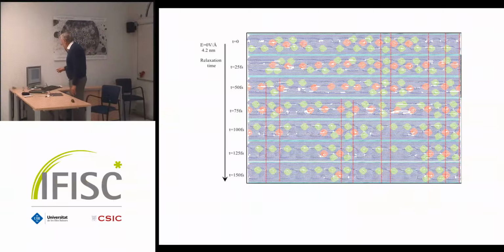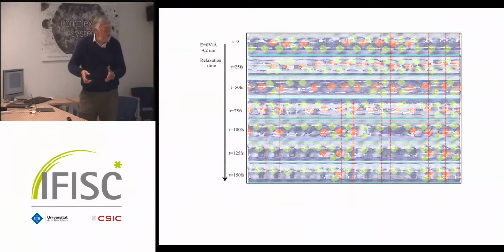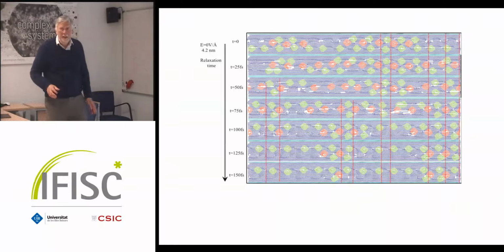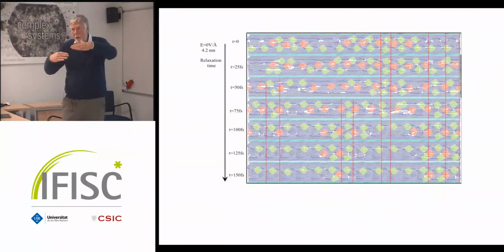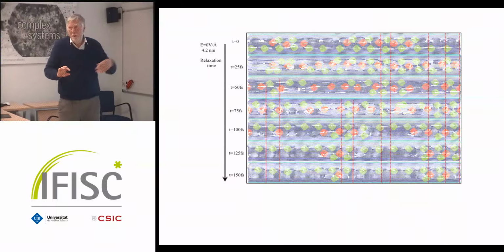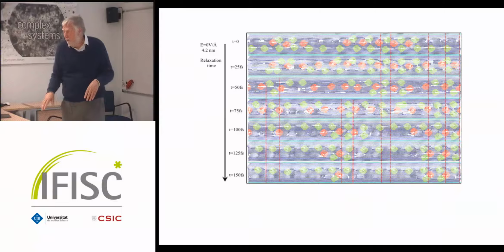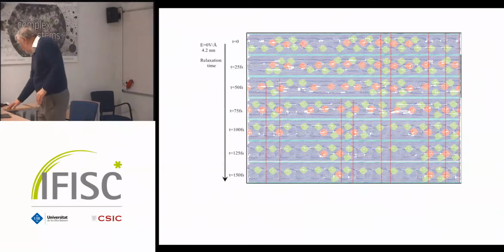Here you can see the vortices are unstripped, so you have a vortex where the lattice deformation rotates, and you can rotate to the right and to the left. To the right is green, to the left is red. So if you have two planes, then the vortex would be in between these two planes. But you can have some, instead of twirling to the right, they twirl to the left, and that is what you see here. So you find from the deviation, the undeformed is the uniform. Then in the uniform you have layers. That's the first level of deformation. Then you have a kink in there, and the kinks are responsible for these patterns here.